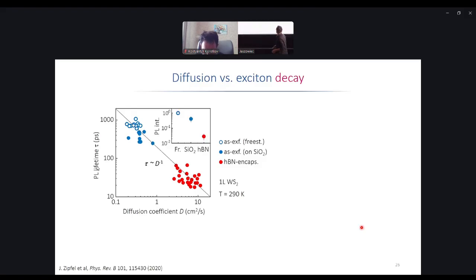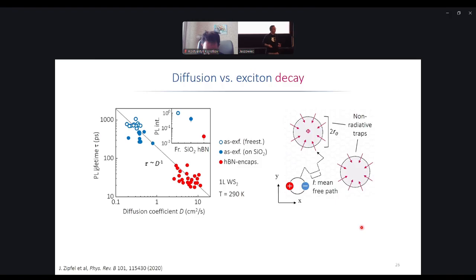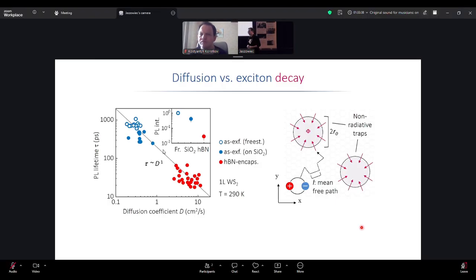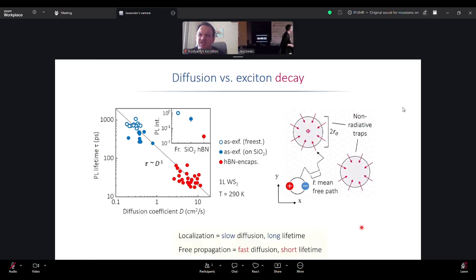So what it means is, if the exciton is slow or even localized, then it takes more time to get there. If I'm slow, it takes much more time for me to random walk towards this defect. If the diffusivity is high, then it's much easier and much more probable to quickly find such a region of non-radiative recombination, and recombine. This is an observation that you can see in many systems, with dielectric disorder or alloy disorder, that if something is fast, then it may find a non-radiative state much quicker. All right, so fast diffusion can mean short lifetime.